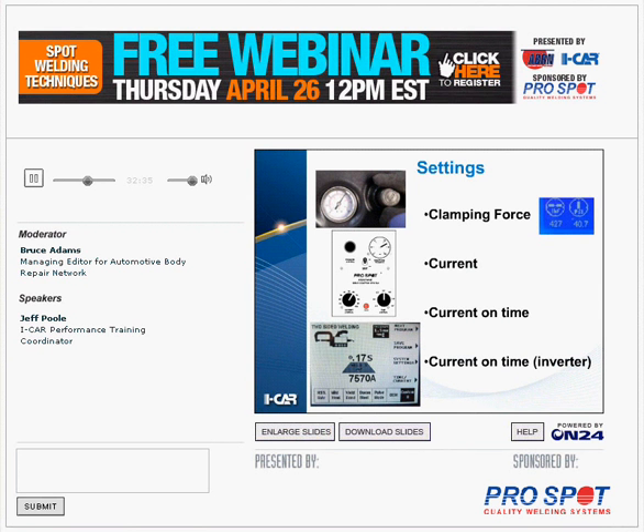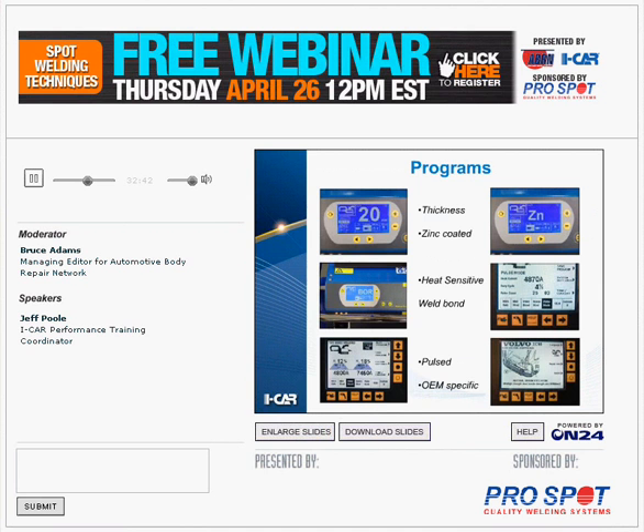With the inverter machines, we'll find that the weld time or the current on time is typically measured in milliseconds. And again, we typically can go into a manual setting mode, and we can tune that up or down as we feel might be necessary based on testing. On machines without inverter technology, the time is typically measured and adjusted in terms of cycles of power based on the power coming in from our service. Again, remember that the inverter welder really makes it possible to apply, I'm going to say, more current over a shorter period of time when compared to most of the non-inverter technologies.